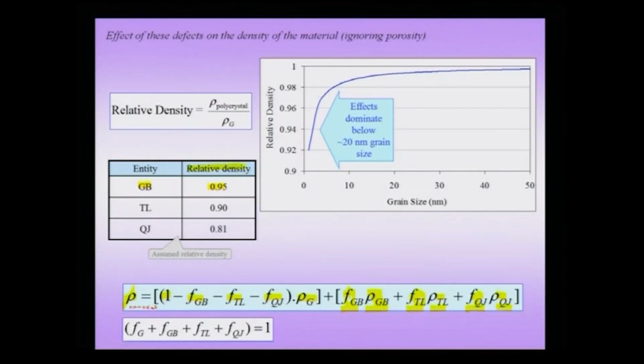That means I am talking about the relative density of the entity with respect to the grain. Suppose the relative density implies the density of the polycrystal divided by the density of the grain. So, for the individual entities, the grain boundary has a 0.95 relative density with respect to the grain, the triple line is about 0.90 and the quadruple junction is about 0.81. That means, as you reduce the dimensionality from grain boundary to quadruple junction, so this is 2D, this is 1D and this is 0D, I see that the density actually decreases.